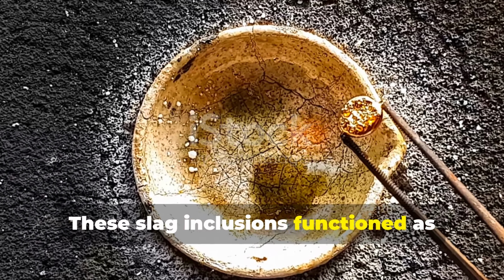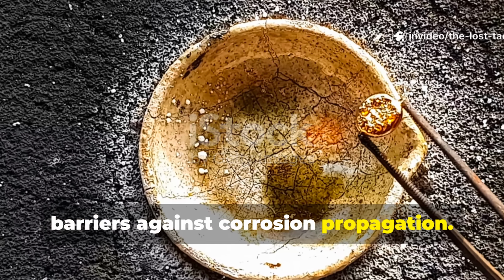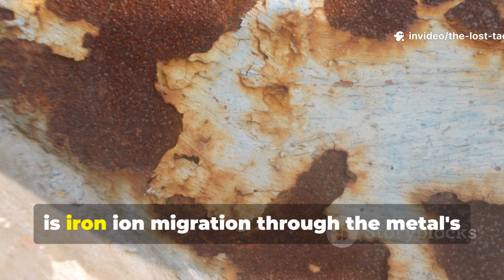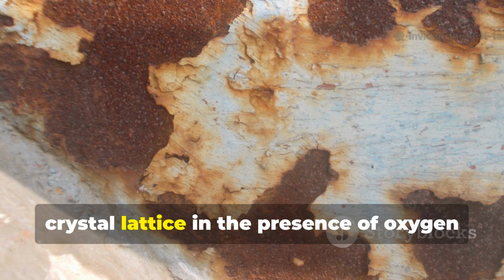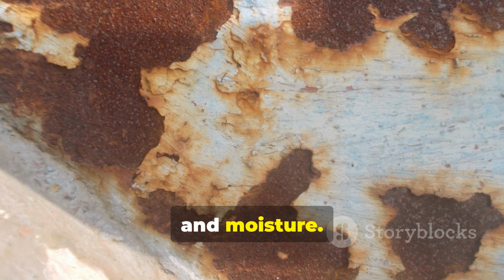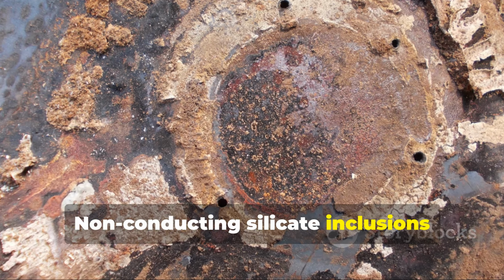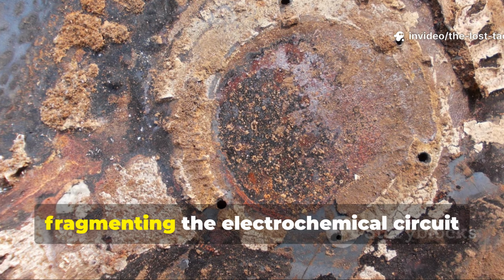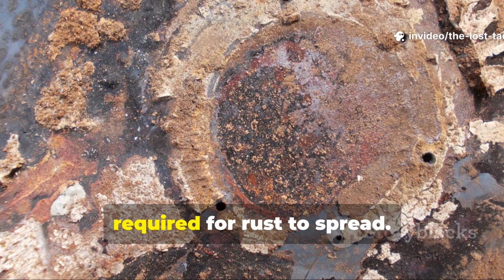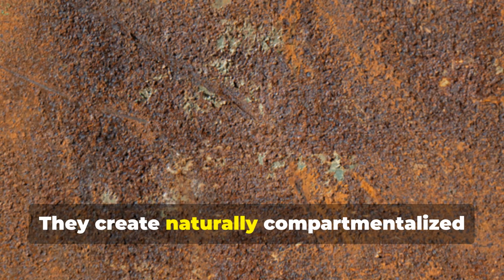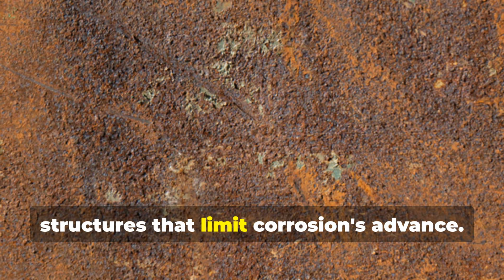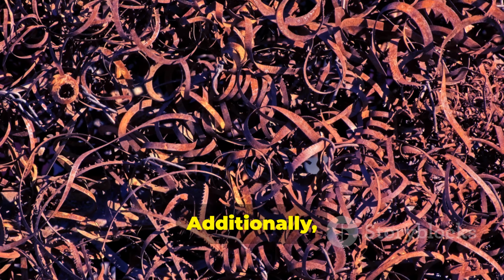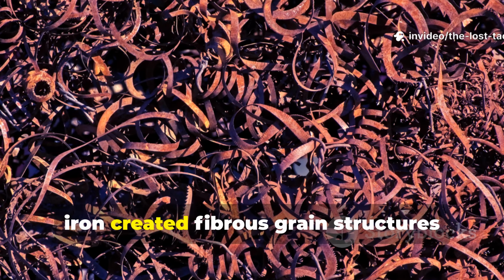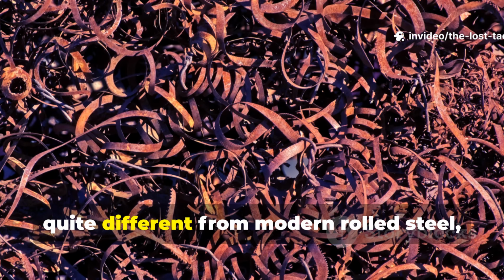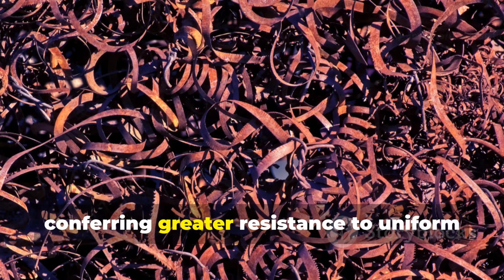These slag inclusions functioned as barriers against corrosion propagation. Rust, chemically speaking, is iron-ion migration through the metal's crystal lattice in the presence of oxygen and moisture. Non-conducting silicate inclusions interrupt this ionic pathway, fragmenting the electrochemical circuit required for rust to spread. They create naturally compartmentalized structures that limit corrosion's advance. Additionally, the working and reheating of bloomery iron created fibrous grain structures quite different from modern rolled steel, conferring greater resistance to uniform corrosion patterns.